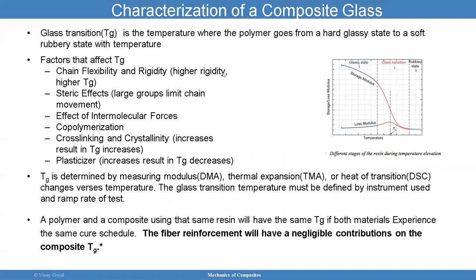So the glass transition is a temperature where the polymer goes from a hard glassy state to a soft rubbery state. As I told you earlier, I will cover it, but I'll repeat it again. So that's the transition we're talking about. There are factors, however, that do affect the TG. That could be chain flexibility and rigidity at the microscopic level, plasticizers used in these prepregs or composites, cross-linking, crystallinity, copolymerization, effects of intermolecular forces, and steric effects, which are really large groups that limit chain movement. All these things affect TG.